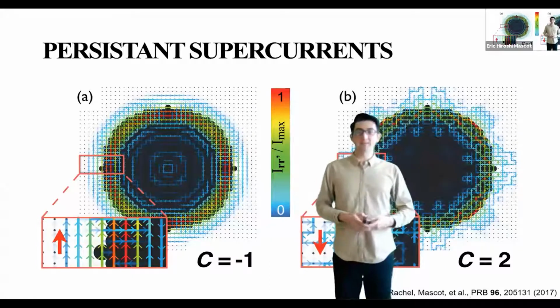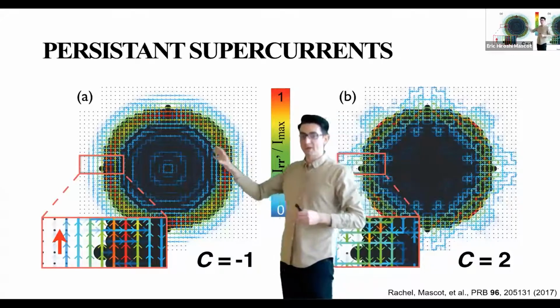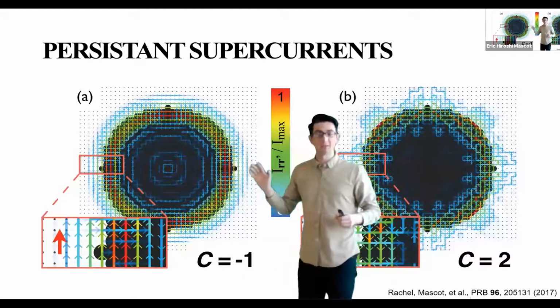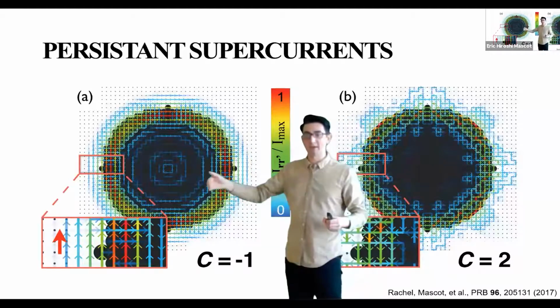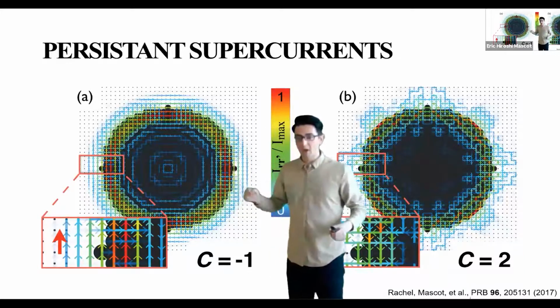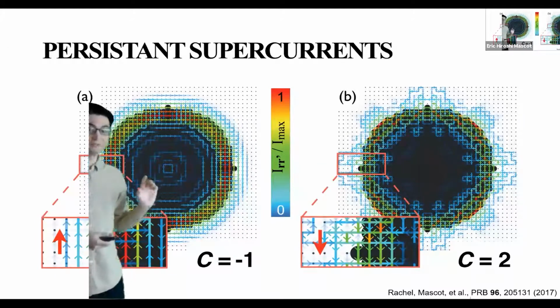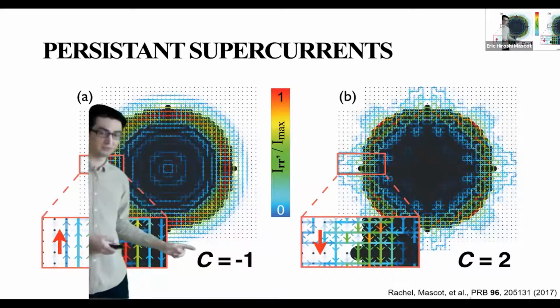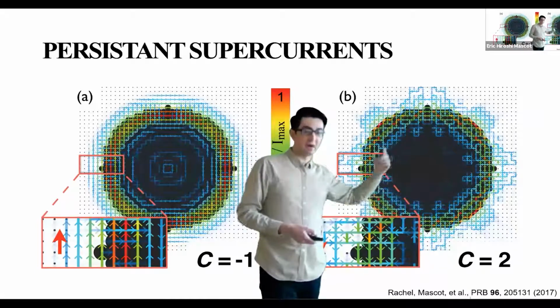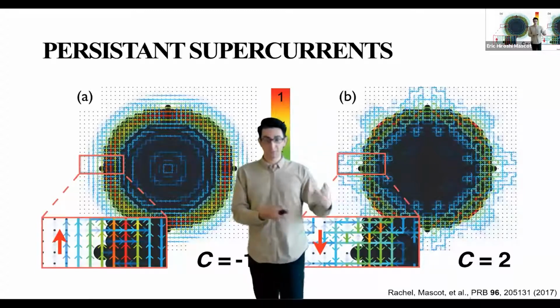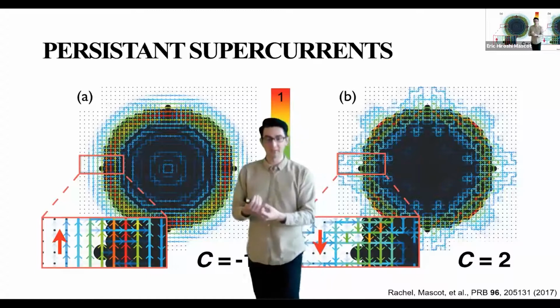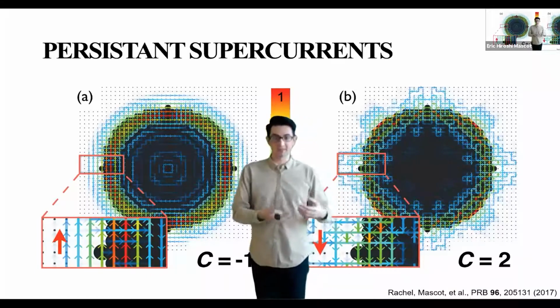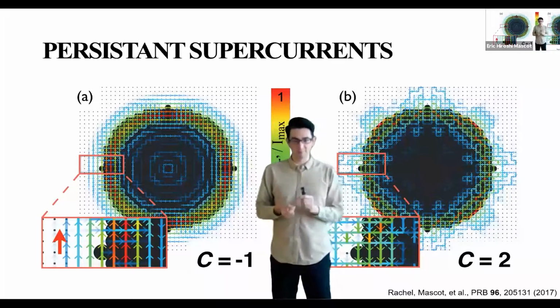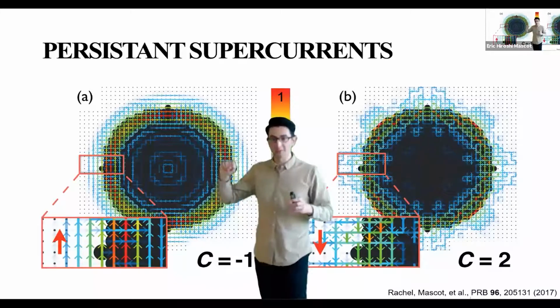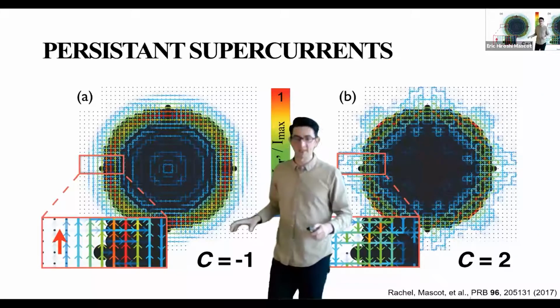Another feature that we found is that you get persistent supercurrents. So you have this magnetic island that breaks time reversal symmetry, but on the substrate, you do have time reversal symmetry. And so at this interface, you get these persistent supercurrents that go around the island. And a unique feature of these supercurrents is that the direction, this one's going clockwise, reflects the sign of the Chern number. So the Chern number is negative here, but for a positive Chern number, we get a counterclockwise supercurrent. And so these supercurrents carry charge, and so the moving charges would induce a magnetic field. So if you have a very fine magnetic field sensor, such as a scanning SQUID or a superconducting quantum interference device that can measure very, very small magnetic fields locally, you would be able to find the direction of these supercurrents and be able to pull out the sign of the Chern number.